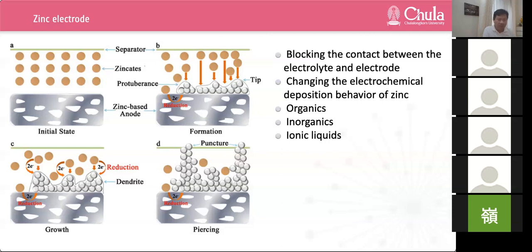That means while you change current density, you can modify the structure of deposited zinc. And the dendritic morphology does not form at low current density due to low activation overpotential. A leaf-like morphology is easily formed at high current density, demonstrating the dendrites symmetrically grow on both sides of the main stems. Such fractal growth may stem from powerful surface energy anisotropy, leading to limited diffusion of atoms.